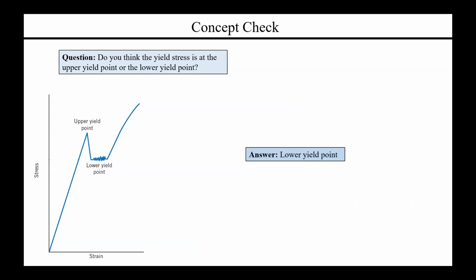So an interesting concept check is what happens when you have this scenario where you're increasing in your linear region, and then you hit this upper yield point, and then a quick drop off to a lower yield point, and then some oscillatory behavior before you pick up again and enter into a nonlinear region. And the question is, given that complicated yielding behavior, what do you think the yield stress actually is? Is it at the upper yield point, or is it at the lower yield point? The answer is surprisingly the lower yield point. And the reason is, if you think back to what yield strength is, it is the point in which there is no longer elastic behavior, right? It is the transition between elastic and plastic.